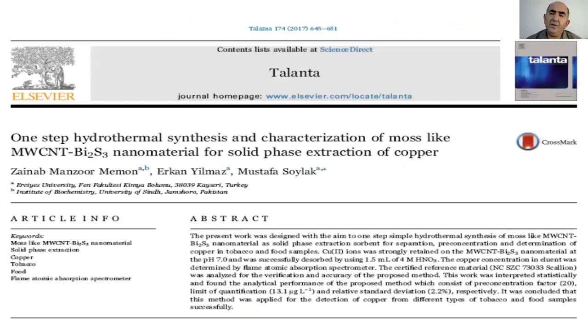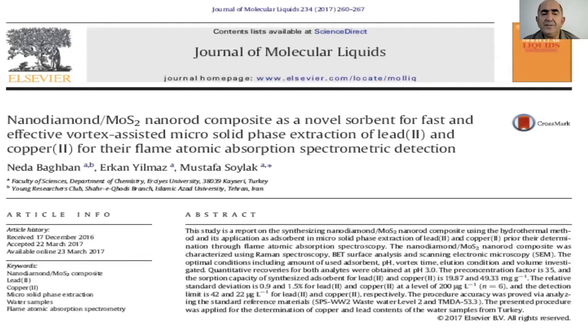Another new material, which is again made by hydrothermal synthesis, is multi-walled carbon nanotubes and bismuth sulfide nanomaterials for the solid phase extraction of copper. As pointed out in the other slides, we did all the characterization steps for these materials. After characterization, we used it for the solid phase extraction of copper ions. Another example is nanodiamond plus molybdenum sulfide nanorod composites for the solid phase extraction of lead ions.